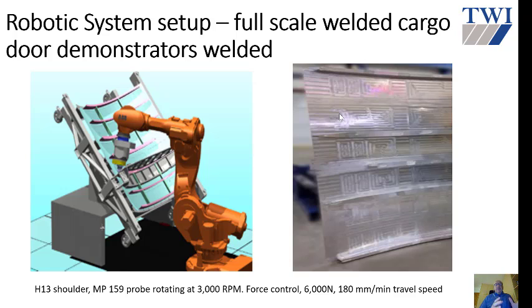So in this case, you can see that the probe was basically a cobalt nickel superalloy rotating at about 3,000 RPM, 6,000 Newton. This is relatively slowly welded, although could have gone faster, but according to TWI, this probe actually had a life of over 500 meters without any breakage or cracking or anything. So very impressive indeed. So what did we do from this point on?